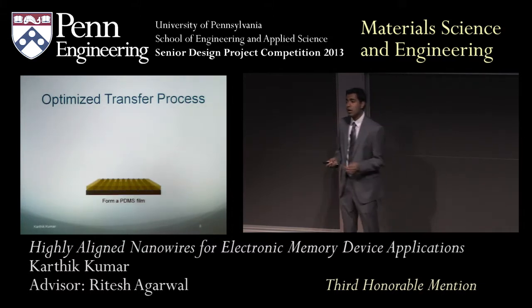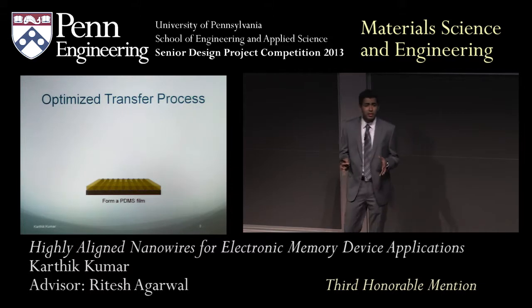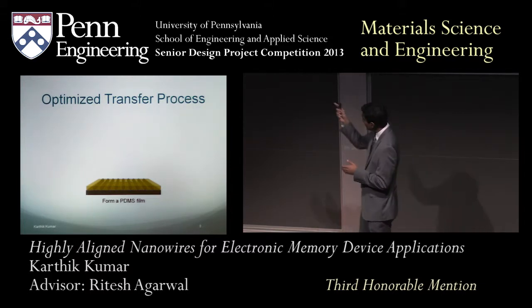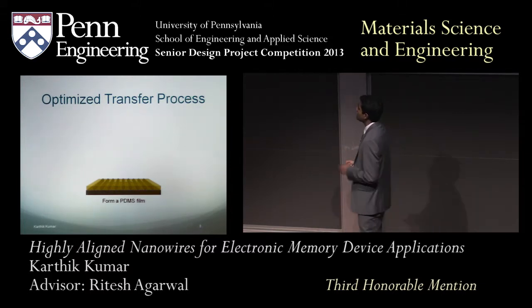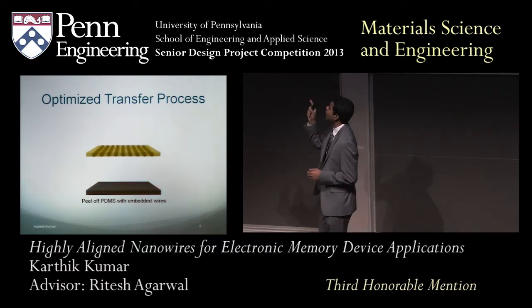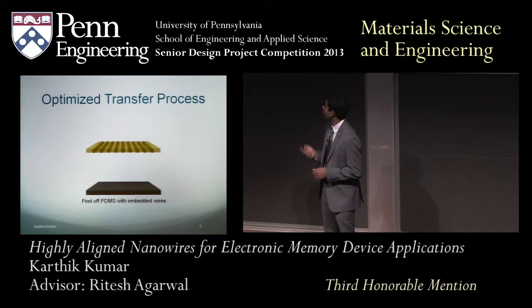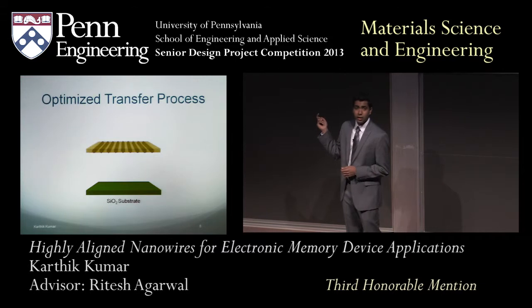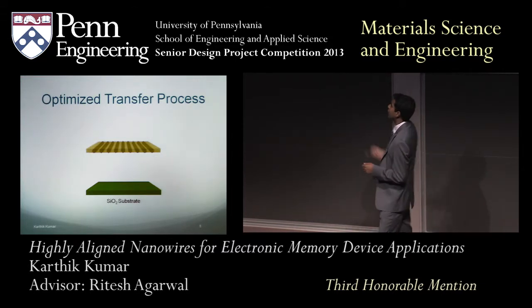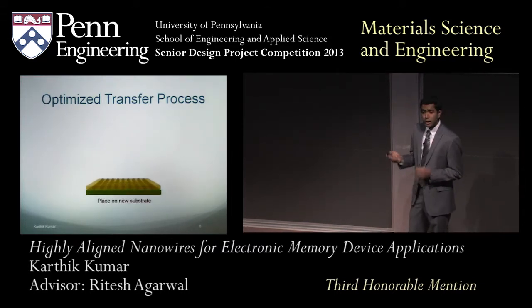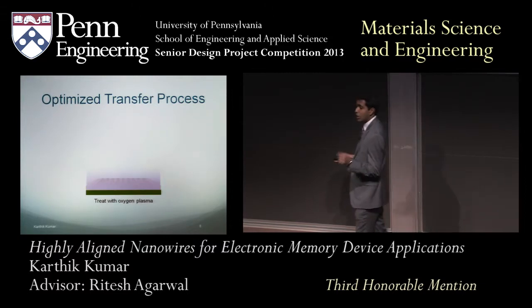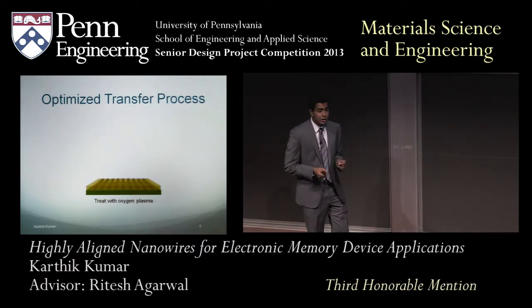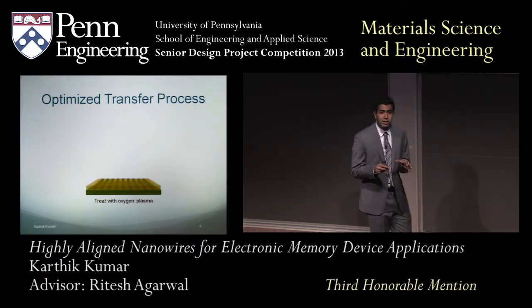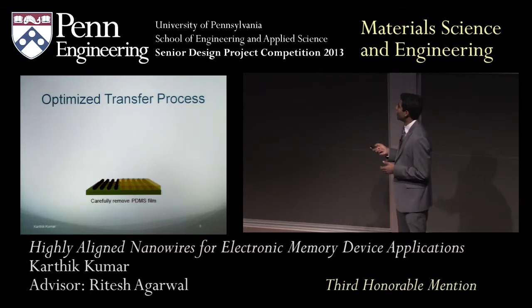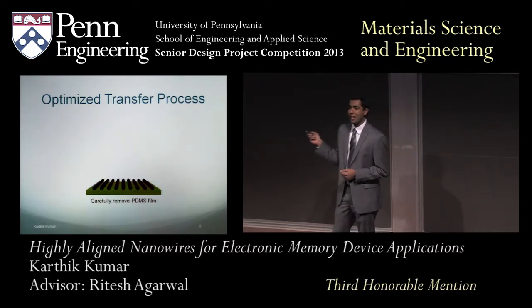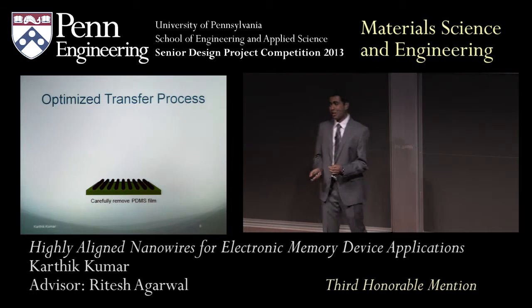PDMS is a highly cross-linked polymer. You can think of it as something very sticky. So we form this film, and once it's cured, we can peel it off, and the wires remain embedded in the film. We can then place that film on our insulating substrate, let's say SiO2. And then here's the key step. We treat it with oxygen plasma. And this oxygen plasma breaks the bonds of these cross-linked polymers, allowing us to remove the polymer, leaving behind the wires. And this really works.